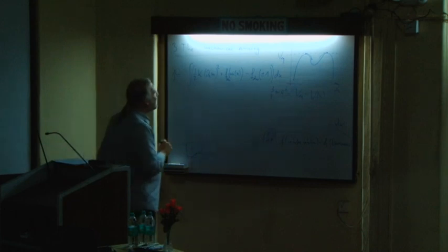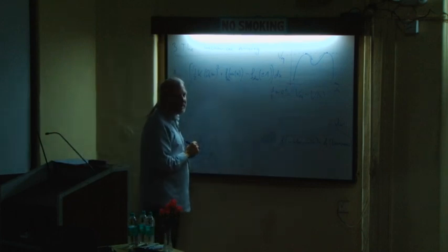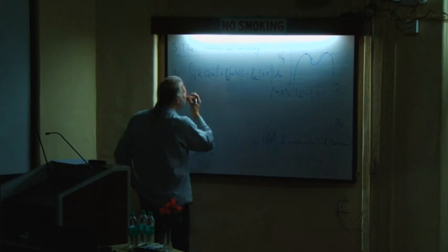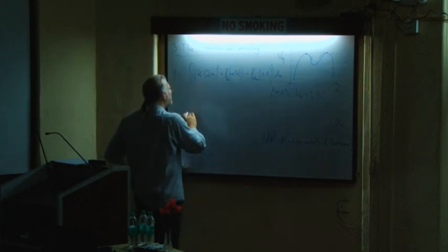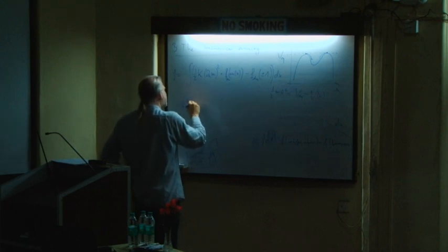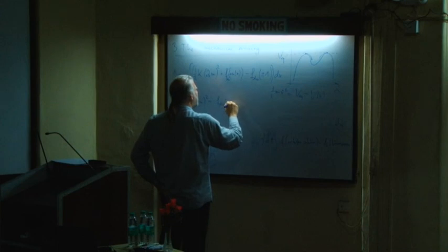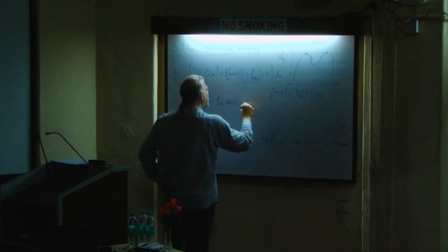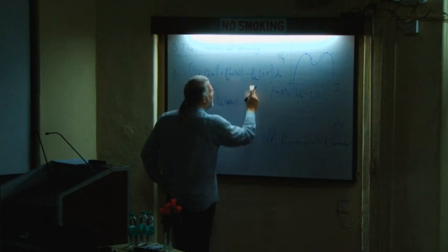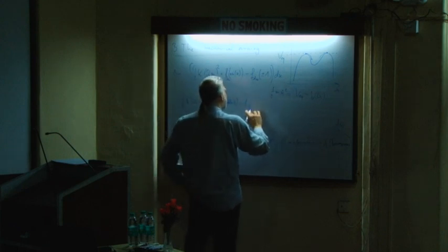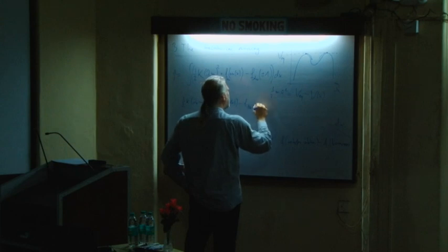And now I can use my equipartition relation that I have wiped out, but I will write again, because from this equipartition relationship we have just gotten that 1/2 k (dxm) squared is equal to f double well of m of x minus f equilibrium, which is precisely f double well of plus or minus 1.